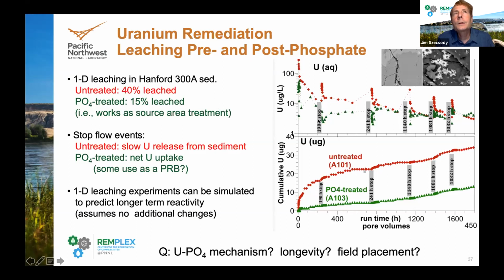Now, the reason I put this on a log scale is these gray bars shown here are stop flow events, where the column experiment typically runs at a constant flow rate, but at these time periods, we literally stop the flow for either 200 hours or 1,000 hours. And there's behavior that shows up there that is actually really interesting. For the untreated sediment, we see the uranium concentration increases. And this just tells us that there's some slow release of uranium from the sediment. Now, it may be that the uranophane that's in these little fractures is slowly dissolving and/or diffusing out of these fractures. This is an image that Hilary showed earlier.